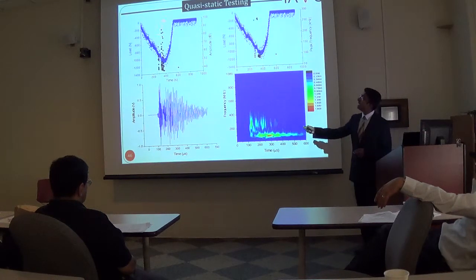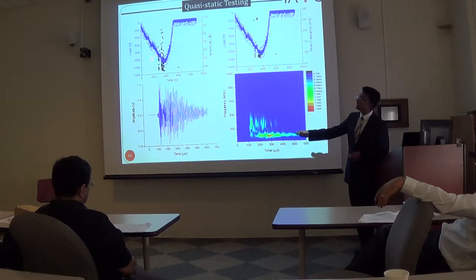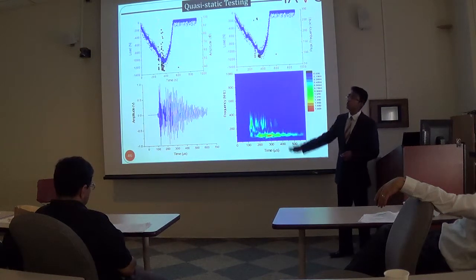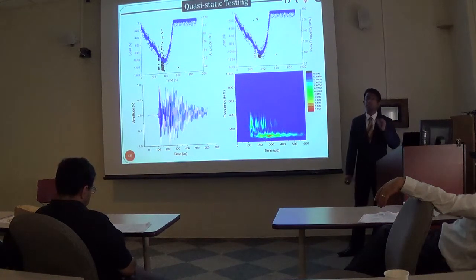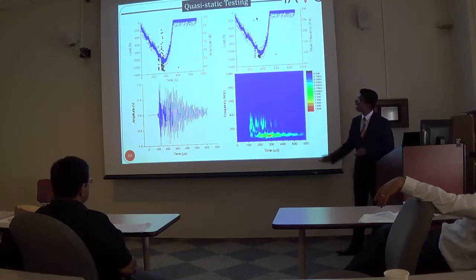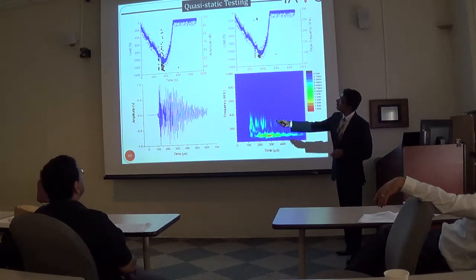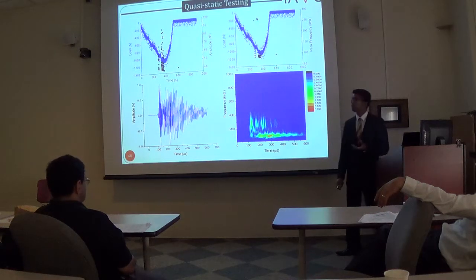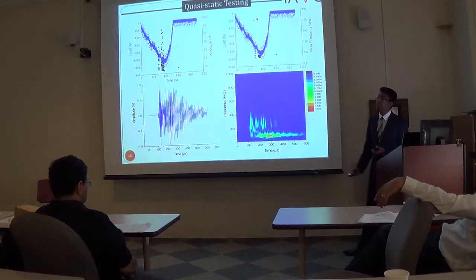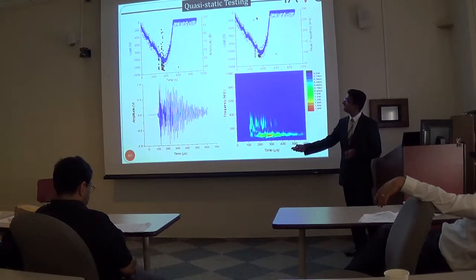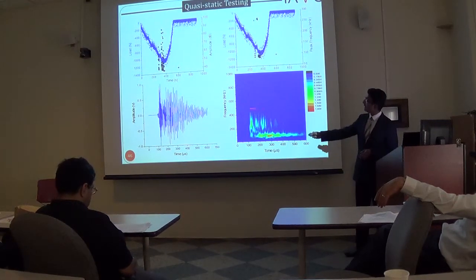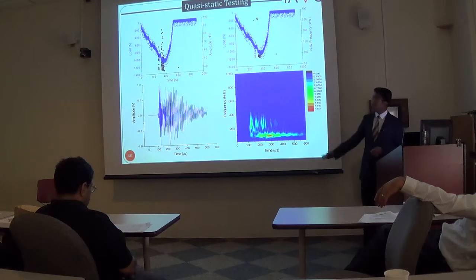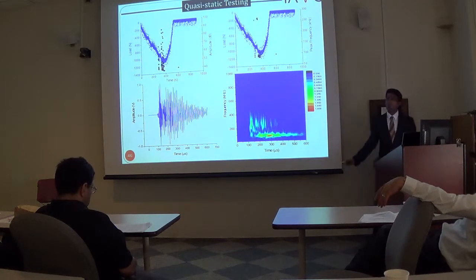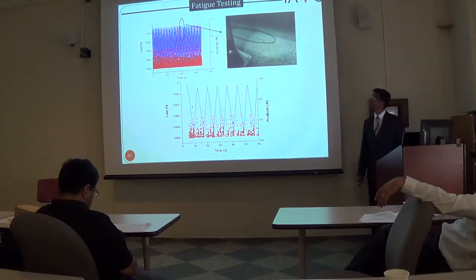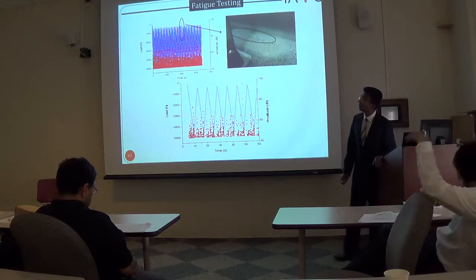Now, what is important to note is AE signals are seen only at the peak load and not at the unloading or in the initial loading profile, and thus can be indicative of actual deterioration in the material itself. Now, further, the AE waveforms that were extracted at this high amplitude and close to peak load show a very interesting phenomenon. It was seen that the waveforms had this dual frequency characteristic, as you can see here, which had an initial large high frequency content, and then later on, had this low frequency content, as you can see here. So subsequently, the skin stiffener components were tested under fatigue conditions to see if we could detect the debonding in it.